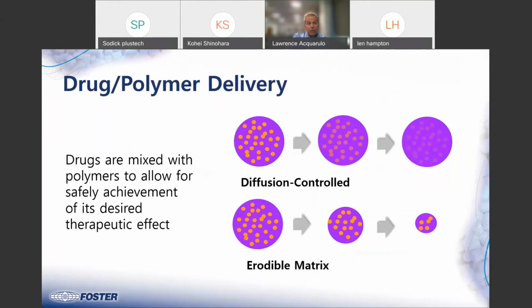Then the drug delivery applications, again, depending upon the polymer that you're using, you usually have two modes of delivery. One is what's called diffusion controlled. This would be a durable polymer, and I'm just going to say an ethylene vinyl acetate or a polyurethane. So you would start off with a material. Typically, it would be an elastomer, so something soft, because the diffusion behaves like a gas or a moisture transferring through the polymer. So you need some mobility through the polymer so that these active ingredients can get out. Depending on the drug load and the polymer, and let's say the vinyl acetate content, you're going to get a release rate. And we have some test equipment that could test for drug delivery release.